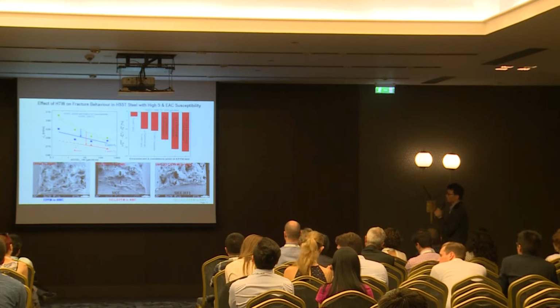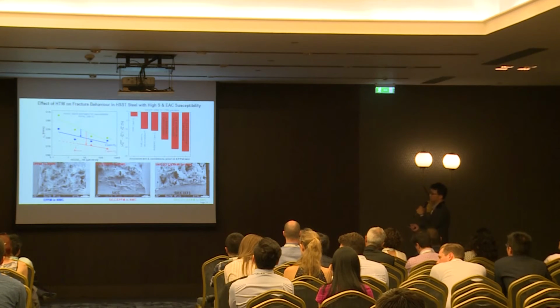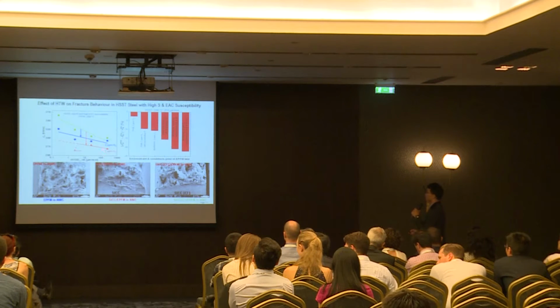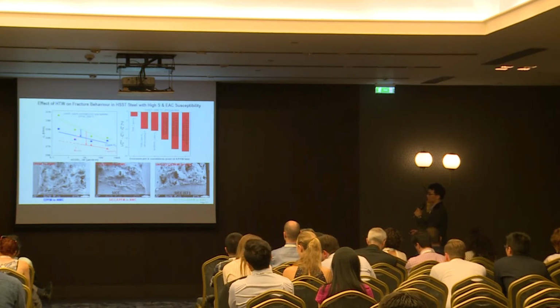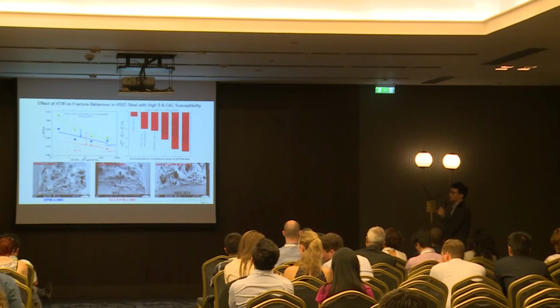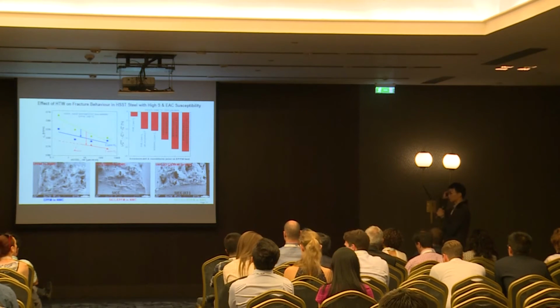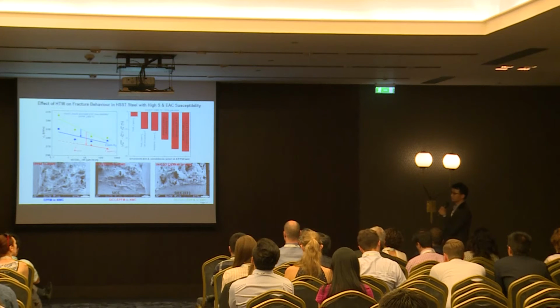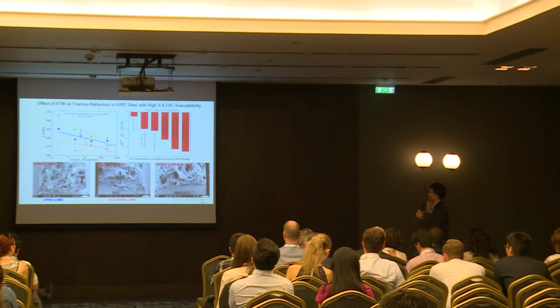Very interesting is when we see the results of the reference material, which has a high sulfur content. The result was totally different, because in this case we have the strongest environmental degradation in oxygenated high temperature water, but not in hydrogenated water chemistry. So this means for steel with high sulfur content, the crack chemistry dominates the environmental degradation.